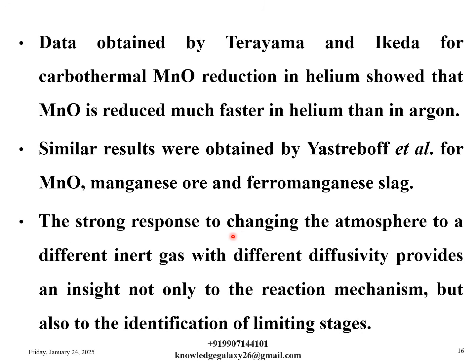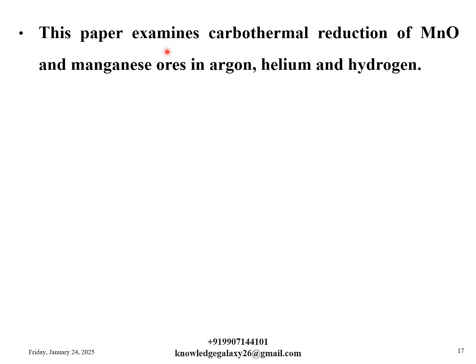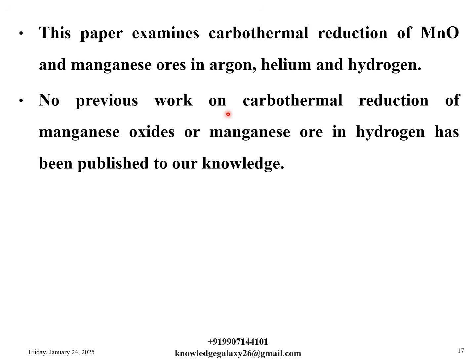The strong response to changing the atmosphere to a different inert gas with different diffusivity provides an insight not only to the reaction mechanism but also to the identification of limiting stages. So this paper examines carbothermal reduction of MnO and manganese ores in argon, helium and hydrogen. No previous work on carbothermal reduction of manganese oxides or manganese ore in hydrogen has been published to my knowledge.